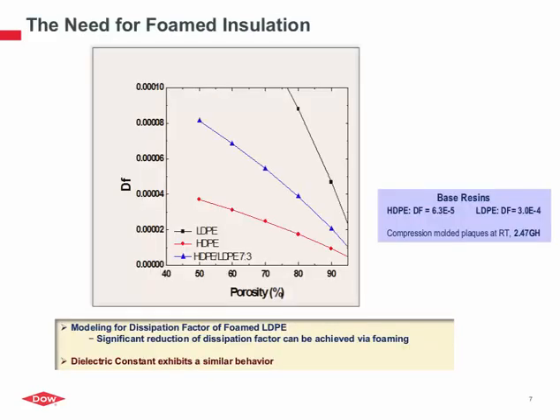Just a brief background of why we need to foam. Number one, what foaming means: if we say 50% foaming, that means 50% of something else, which is really the gas that is entrapped in these cells. And generally, the gases that are in the cells have much better dielectric properties, whether it's air, nitrogen, argon, or carbon dioxide. All of these have better dielectric properties than the polymer that is used. And so that's why, when we foam, in this graph here, it's a simulated calculation of how the dissipation factor responds. And you can see it's a significant reduction in the dissipation factor by foaming. Here we are presenting the dielectric dissipation factor, but the same goes with the dielectric constant itself.